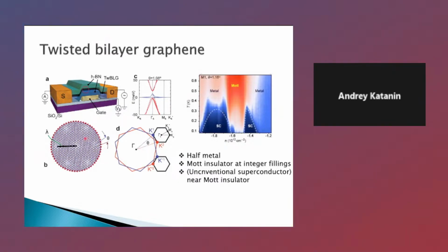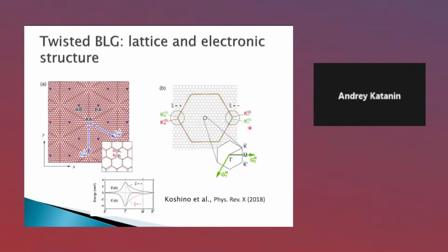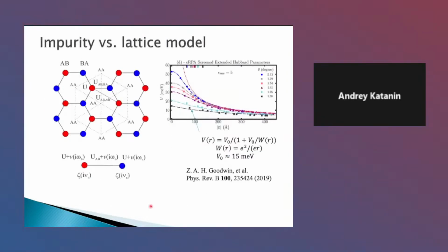These are two sheets of graphene rotated by a small angle with respect to one another, and this produces well-known narrow bands and a Mott insulating state at some fillings and superconductivity near these fillings. So we take the ab initio dispersion which was obtained in this paper, shown here to the left, and we take the ab initio Coulomb interaction, which for small rotation angle is shown here by the black line, and it can be parameterized by this dependence on the distance.